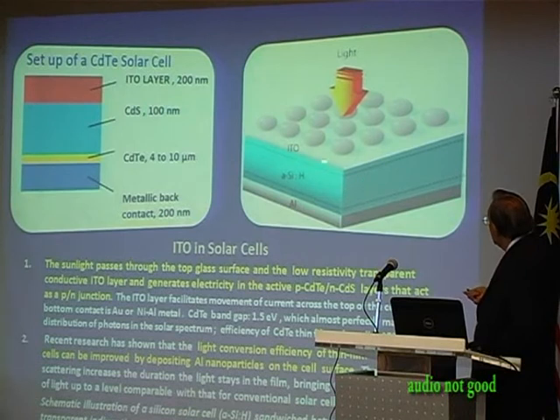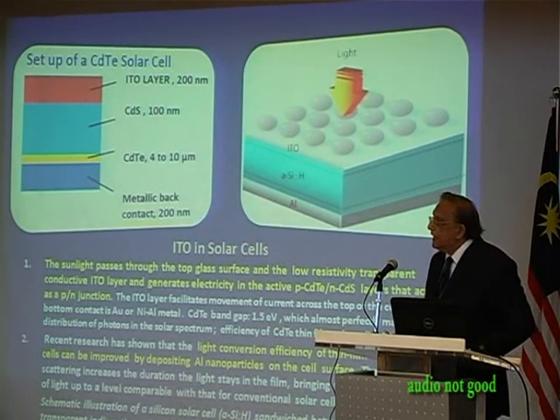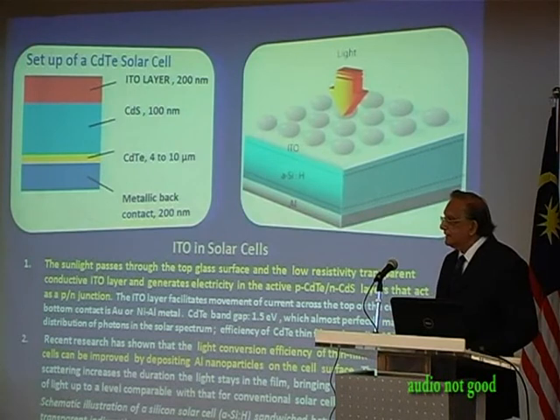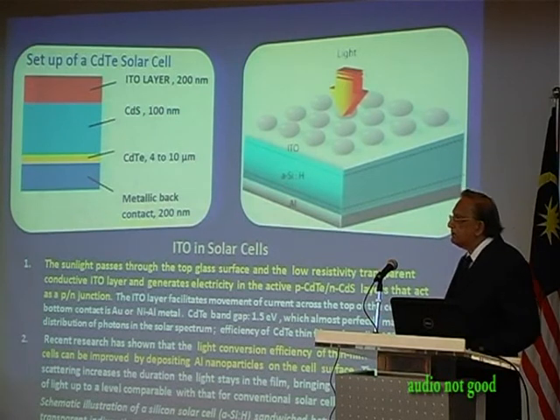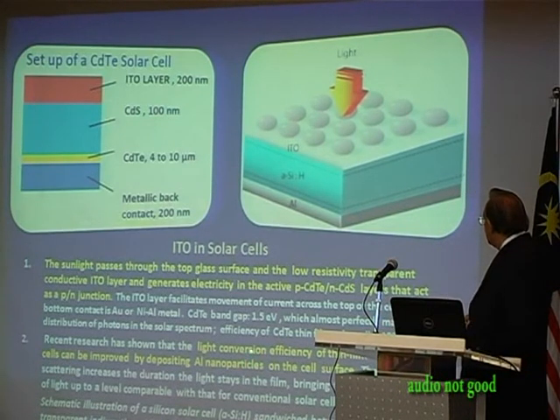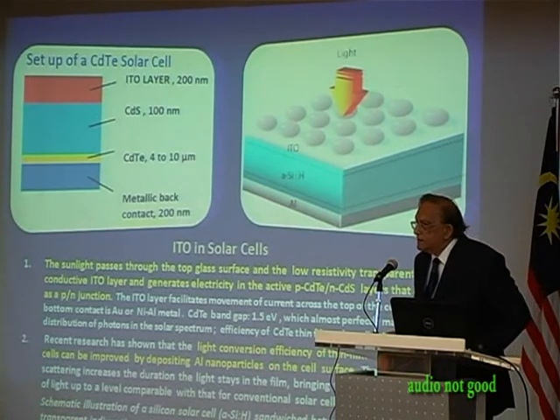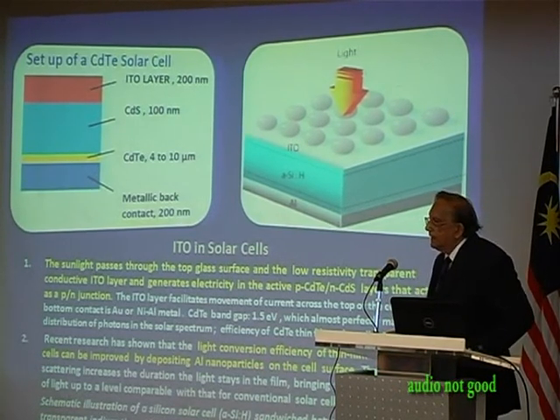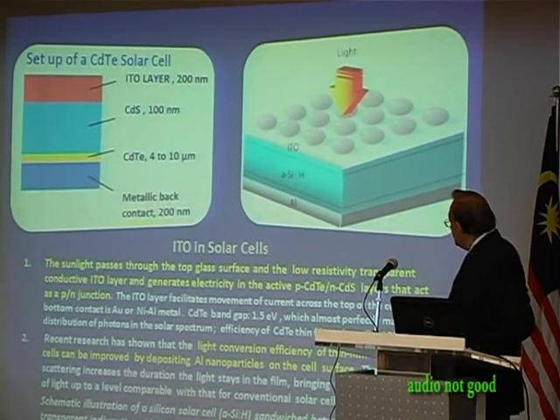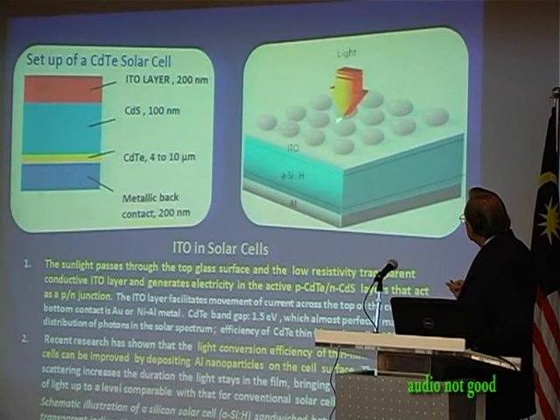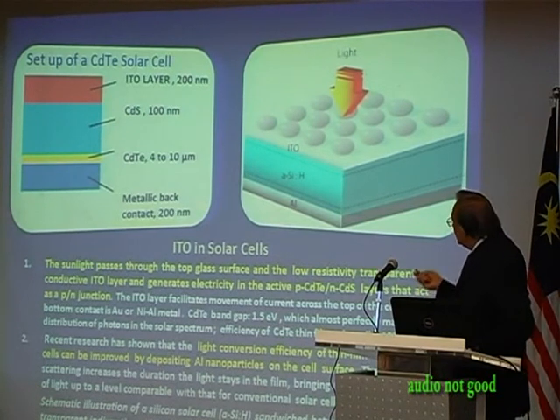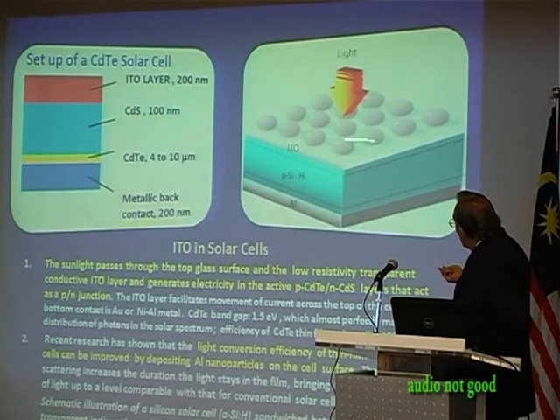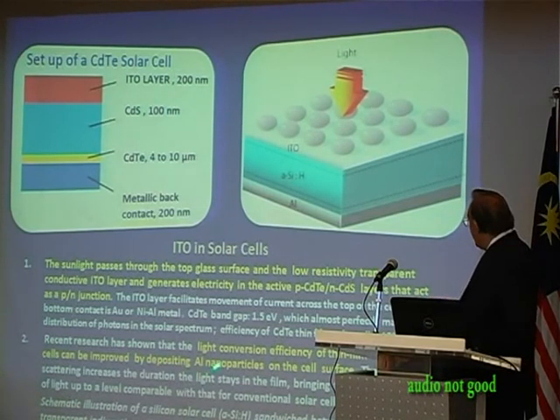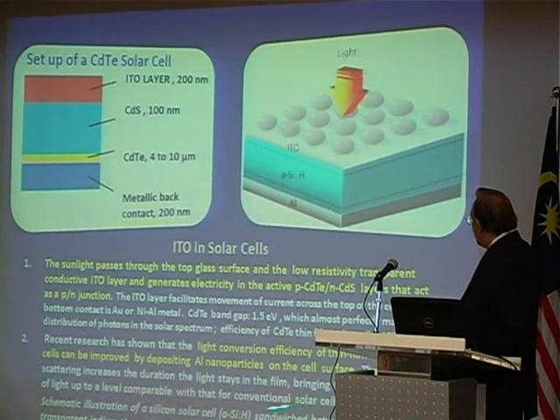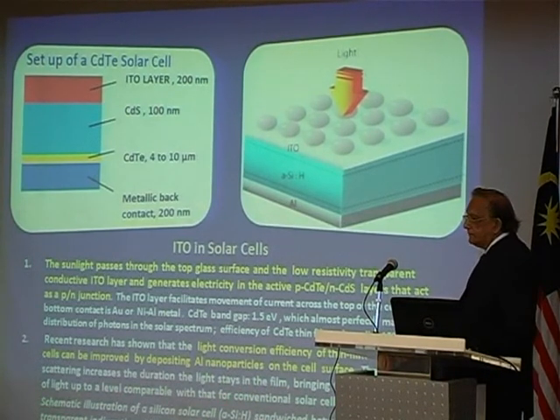Now the gold standard is of course the silicon crystal wafer. They have tried to make thin films of amorphous silicon, but the problem has always been that the light conversion efficiency is low. But researchers have put aluminum nanoparticles on top of that ITO, and these absorb and scatter the light, so the light stays on the surface, and apparently the theory is that the total absorption increases.